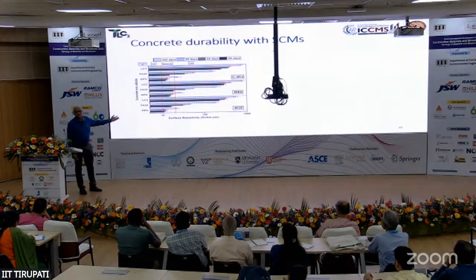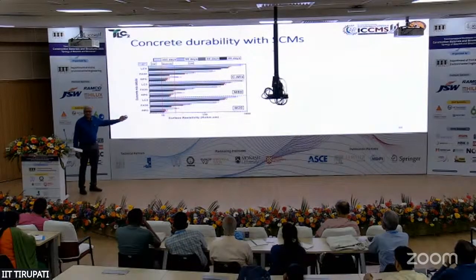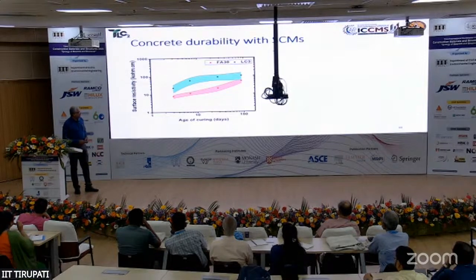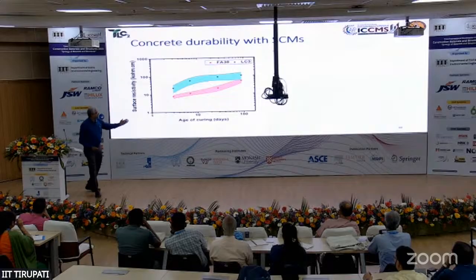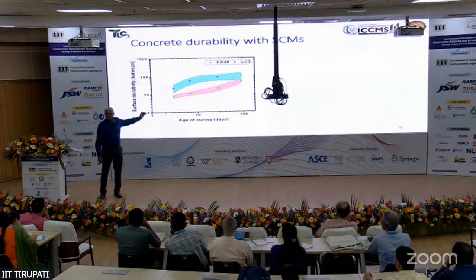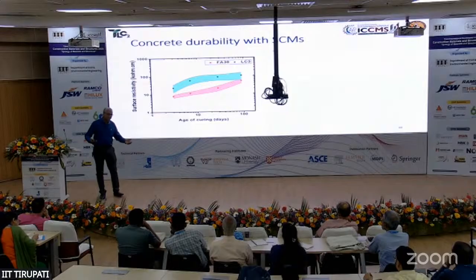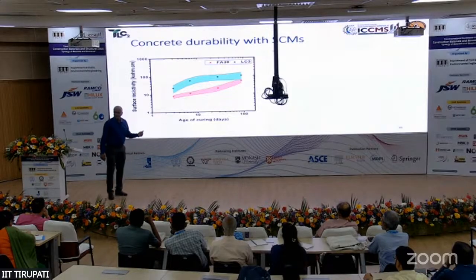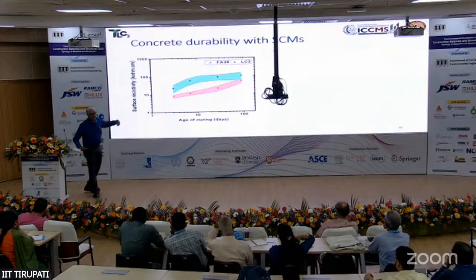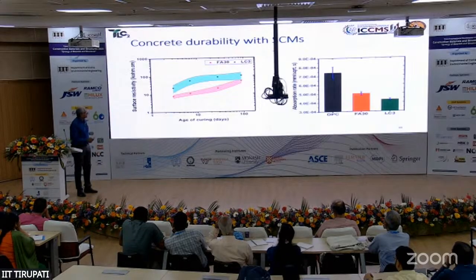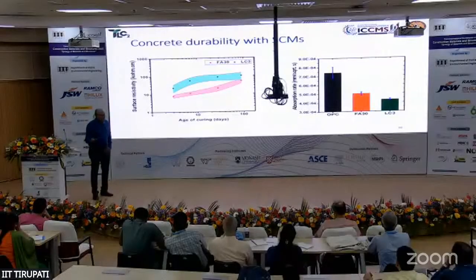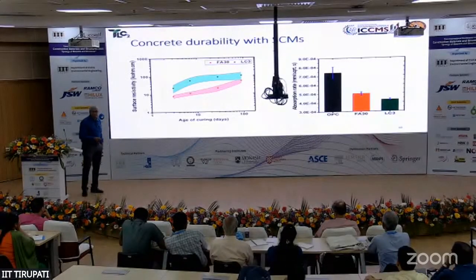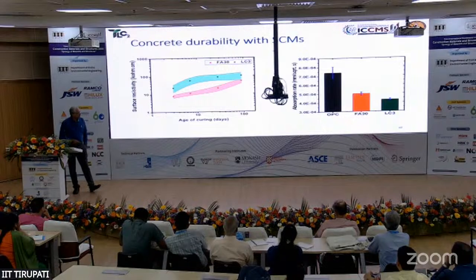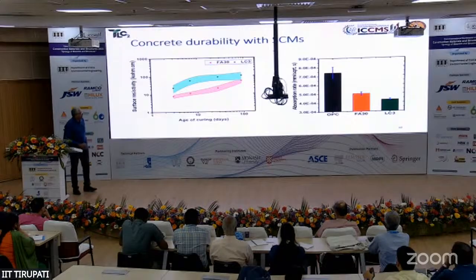So you do get much lower permeability in the LC3-based systems as compared to OPC. If you look at resistivity development with respect to time, you can see that compared to fly ash-based systems, which eventually develop the same level of resistivity, the LC3-based systems are developing this much faster, obviously because calcined clays are a lot more reactive, and that reduces the overall conductivity of your system and improves the resistivity at an early age. Now, in terms of water absorption rate, again, this is the ASTM test method, which looks at the water absorption in the very early stages. You can clearly see again that the concrete with mineral additives performs much better than the ordinary Portland cement concrete.